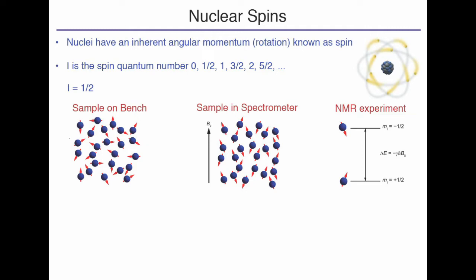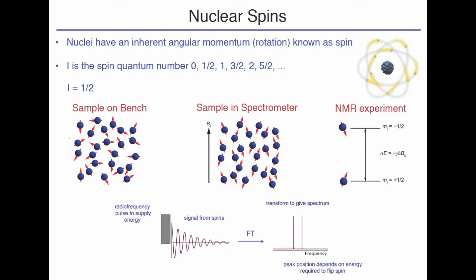What an NMR experiment is doing is basically trying to provide enough energy to get these spins to flip, to go from being aligned to being not aligned with the field. We can apply a pulse to get this energy difference to make the spin flip. Then we listen for the response from the spin, and that's where all the structural information is. Once we listen for this response, we can do a Fourier transformation, which is just a mathematical manipulation, to get peaks in a format where we can actually see some structural information. The actual position of the peak will depend on the energy that was required to make that spin flip.